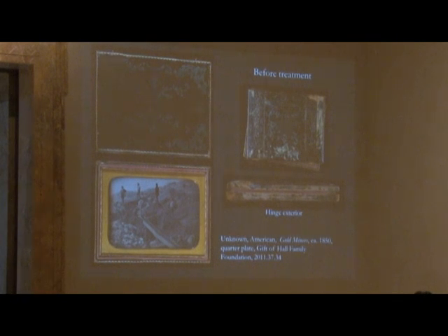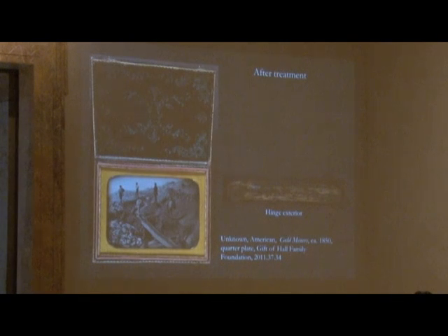So what I did for this piece was to first lift the leather along the spine on the exterior and interior side. Then I prepared a Japanese paper strip and toned it to match the color of the original leather, inserted it between the wooden frame and the leather, and set it down with adhesive. Japanese paper is very thin, so it doesn't add bulk, but it's really strong and it stays flexible for a long time. So it's a really ideal material for repair of the hinge. I do work on the inside first and then do the exterior. This is after treatment.